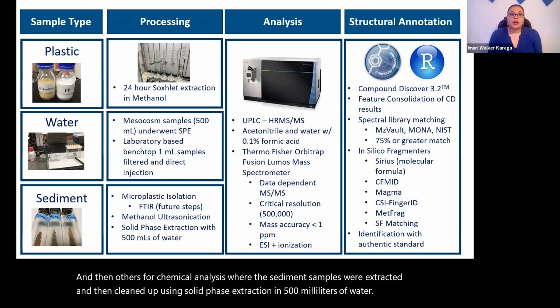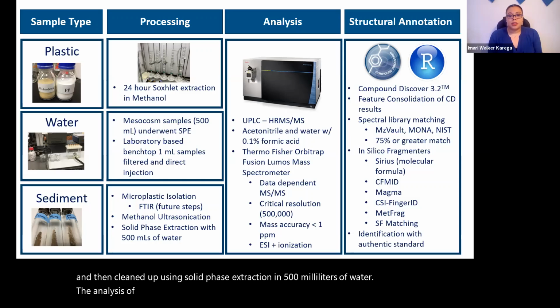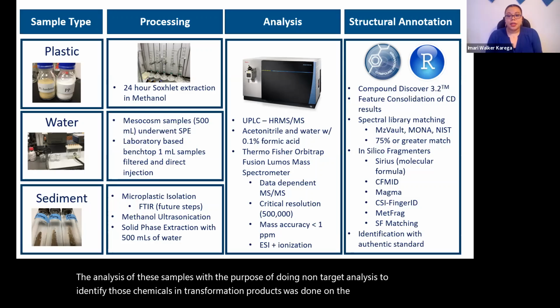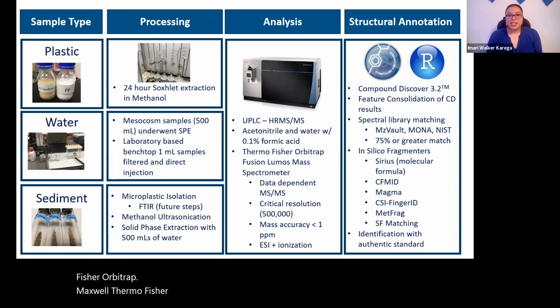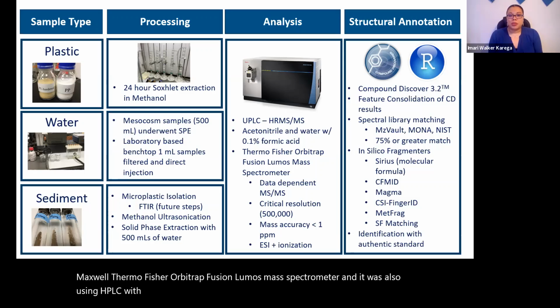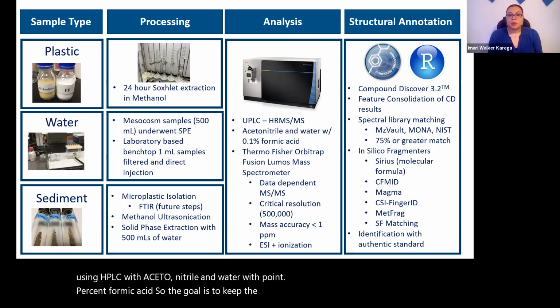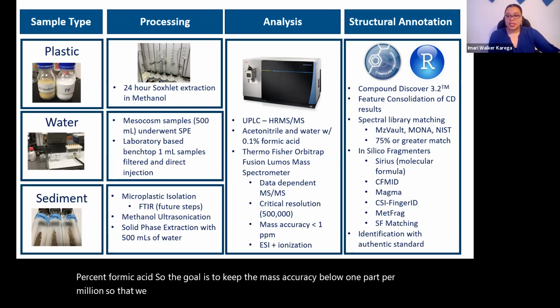The analysis of these samples, with the purpose of doing non-target analysis to identify chemicals and transformation products, was done on the Thermo Fisher Orbitrap Fusion Lumos mass spectrometer, using HPLC with acetonitrile and water with 0.1% formic acid. The goal was to keep the mass accuracy below 1 part per million so that we could do really good identification of these compounds.